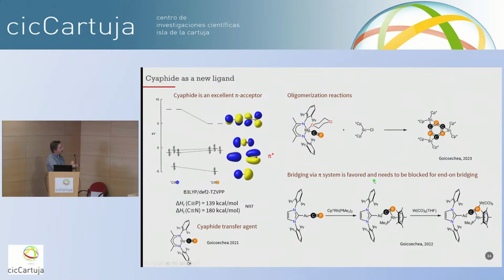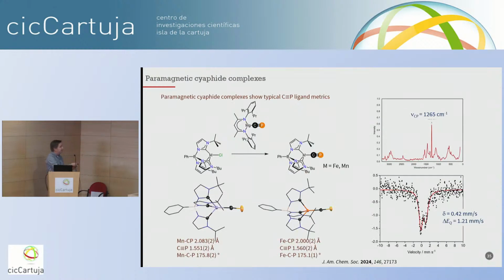And another thing that's really important about cyaphide is that phosphorus here is not particularly nucleophilic. So for example, if you try to substitute on rhodium with cyaphide, actually the rhodium binds to the pi bond. And only when you block this can you bind another metal. So we were interested in looking at this for just paramagnetic complexes. So we can take either iron or manganese compounds with their cyaphide transfer reagent. We can make these cyaphide complexes.